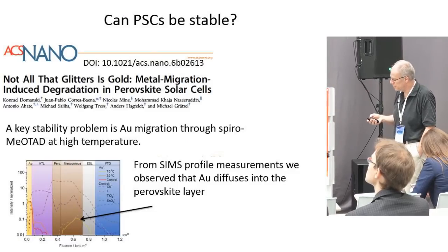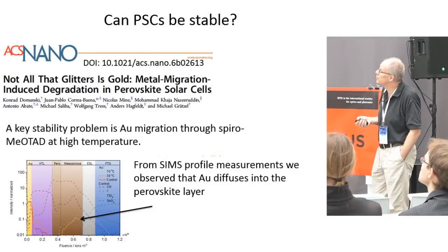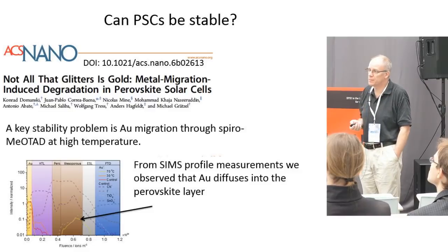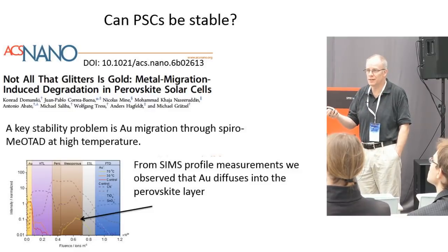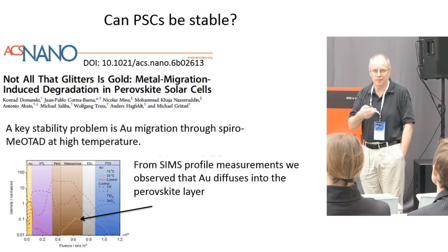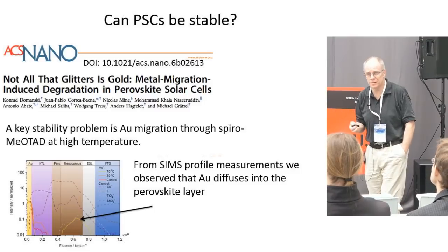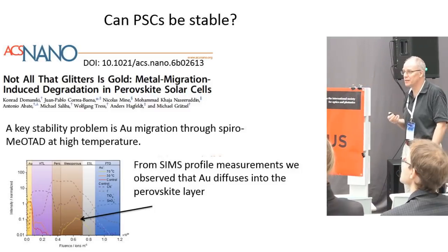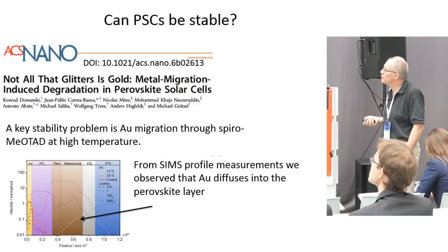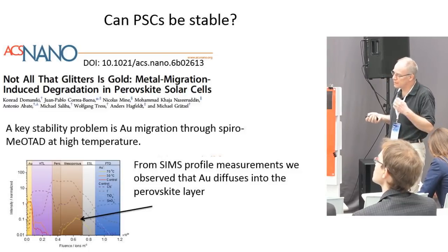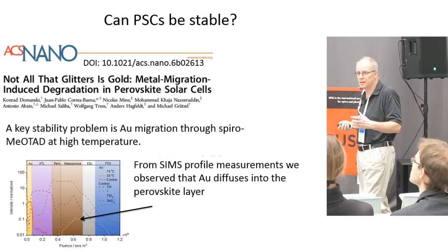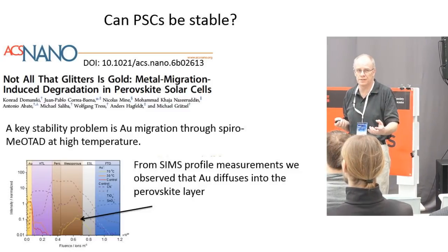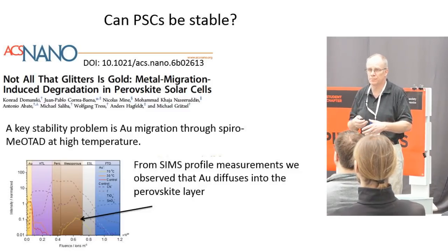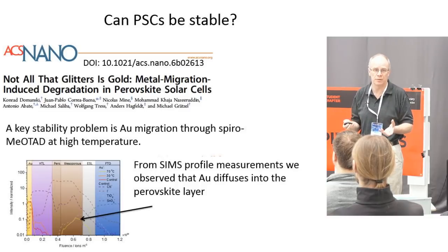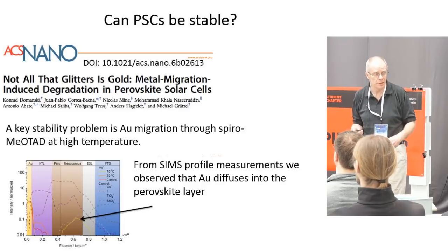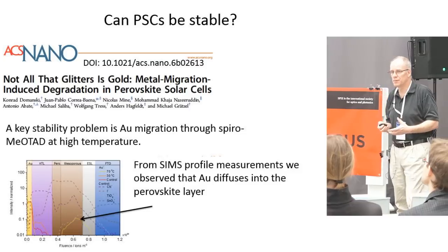I'm coming to the end because I'd like to mention a little bit also on stability, because this, as I said, was in the beginning 10-minute stability. How does it look now? And there are all reasons to think that it's difficult to get it stable. We investigated the stability and saw that high temperature was really killing the devices. When we took it to 85 degrees, the efficiency dropped from 18, 19 to 3, 4. Completely dead, almost.